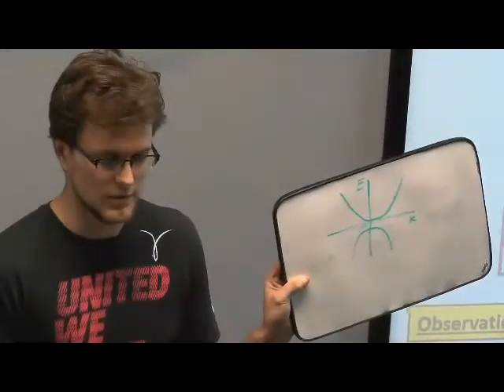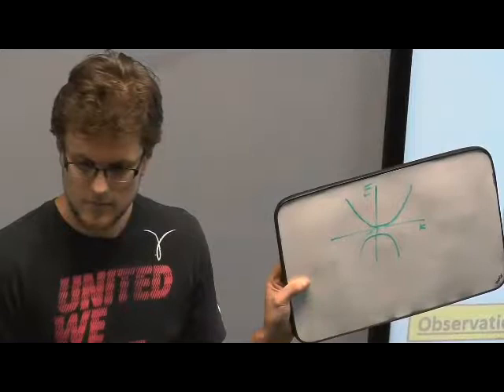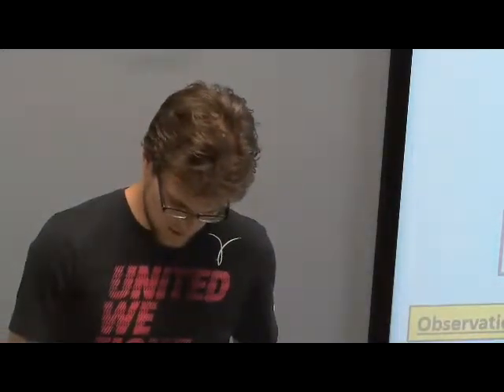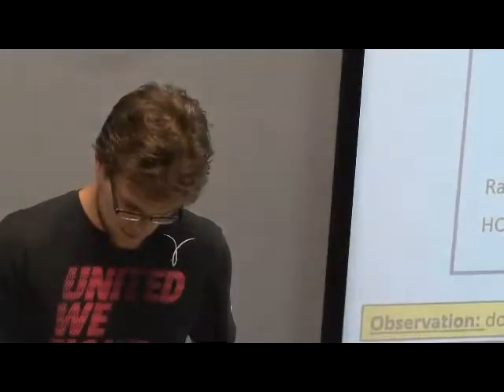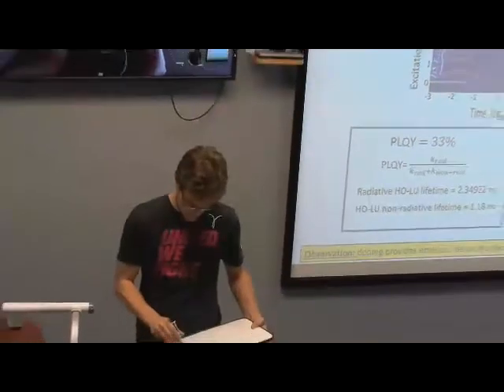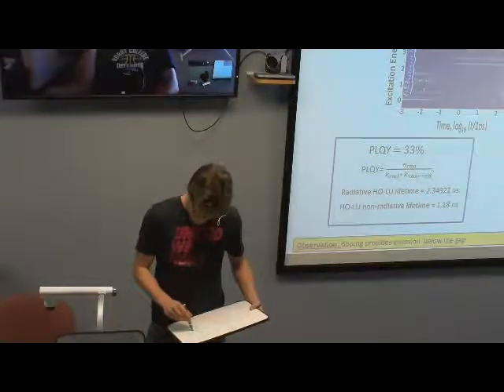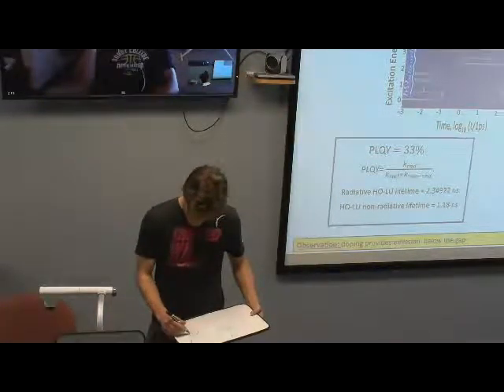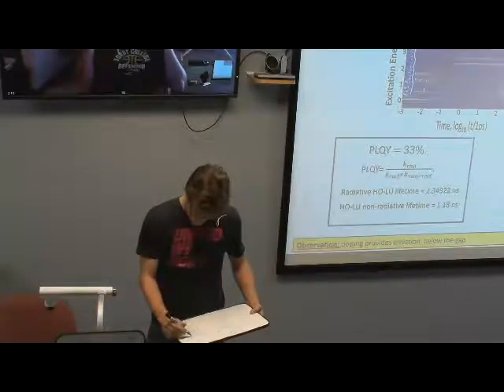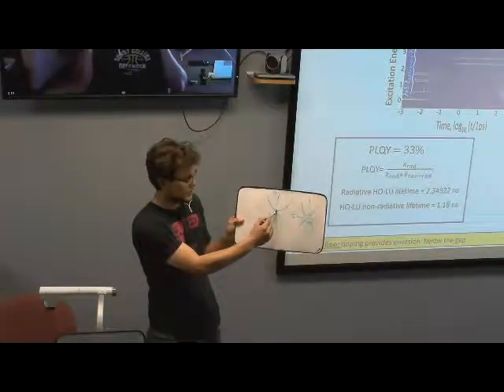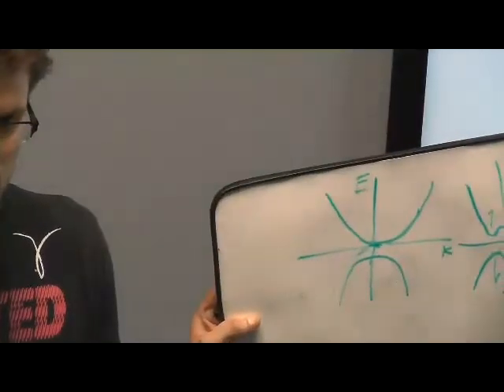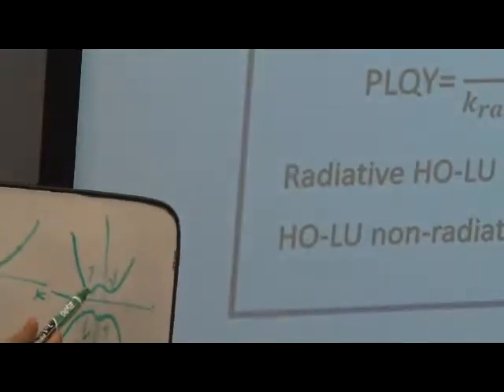But if you have spin orbit coupling with, I can't remember what the technical term is, but any sort of crystalline defect or asymmetry within the crystal, you can get spin splitting of these bands. So it would look more something like this, then momentum dependent spin splitting. Normally you just have one minimum for your dispersion curve. But when you include the Rashba effect, you get two minima, which are spin dependent.